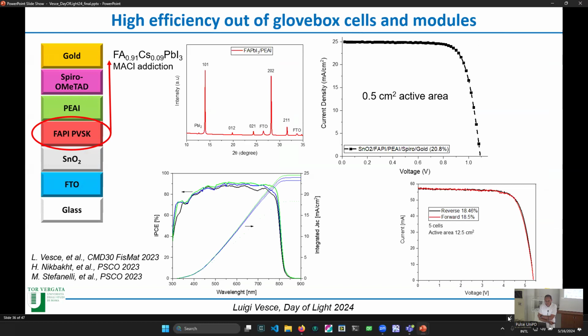Okay, but we want to further improve the efficiency of our module, and so we start to change the perovskite composition. Essentially, we work on this FAPI perovskite, that is a very narrow band gap perovskite, and we deposit the perovskite with the process which I showed you before, with this double step process. We got this very good efficiency, approaching 21% on small area cells, on 0.5 square centimeter active area, and that is also testified by the integrated current. And then we realized some modules, some mini modules, with a maximum efficiency of 18.5%.